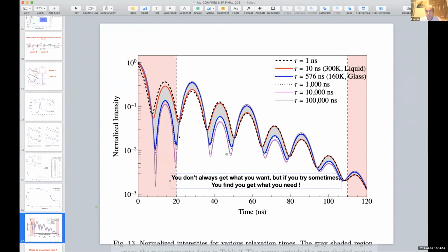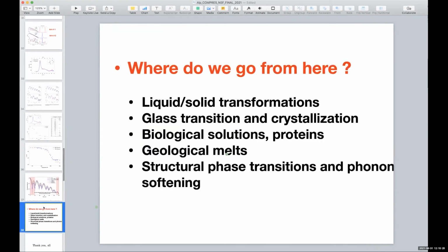So even though the first 20 nanoseconds at APS is blocked, we cannot really see it, and the last 10 nanoseconds is blocked, the in-between window provides us sufficient selectivity where we can go from 1 nanosecond, the dotted line, up to 10,000 nanoseconds. So our sensitivity range in this new spectrometer covers 4 or 5 orders of magnitude. One minute. So, yeah, where do we go from here?